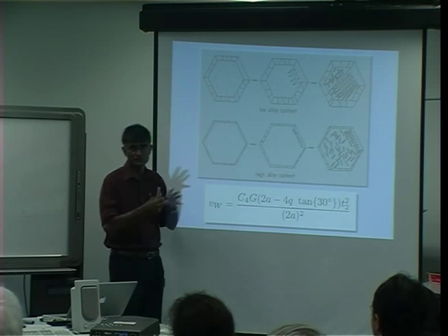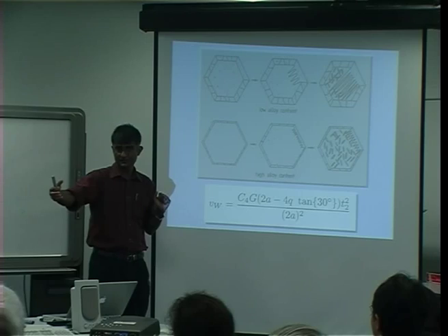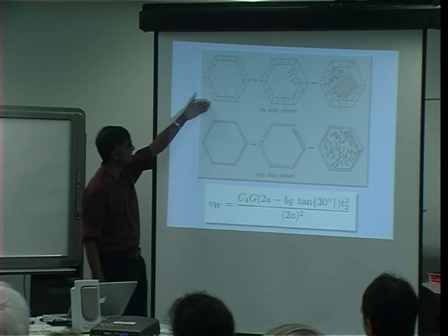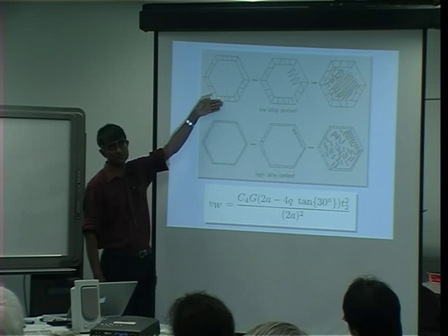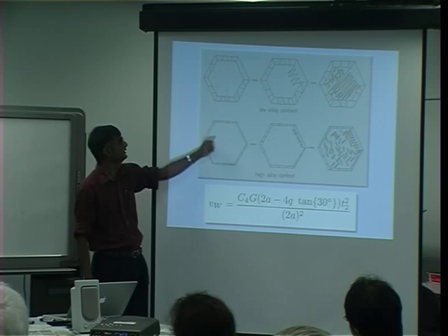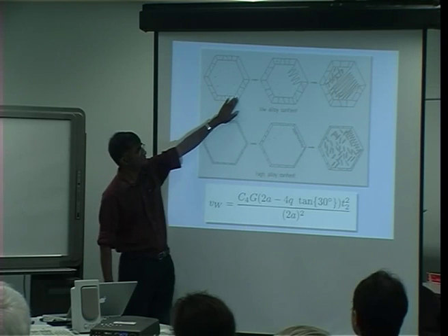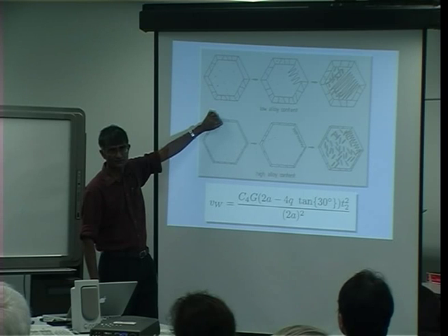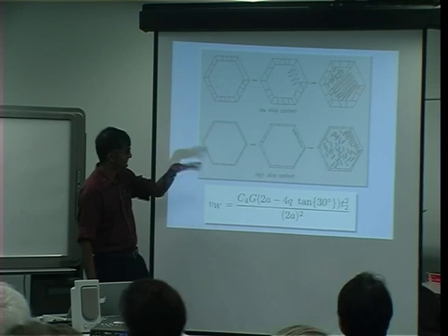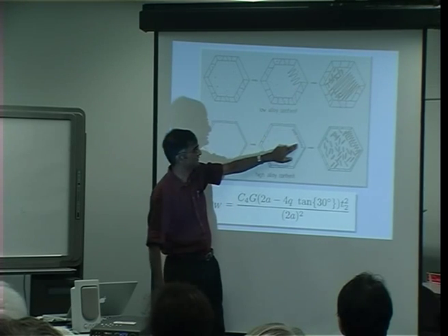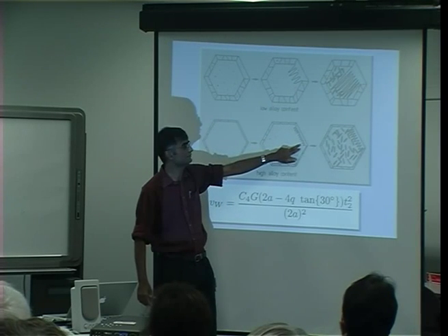This is a cross-section of that columnar grain. Okay. So it's a hexagon. And I'm going to compare a steel in which transformation is rapid and a steel in which transformation is slow. Okay. So here we have a layer of allotriomorphic ferrite forming at the boundaries. And of course here there will be a thinner layer of allotriomorphic ferrite. The temperature drops, I get rapid Widmanstätten ferrite growth here, I get relatively slow Widmanstätten ferrite growth.